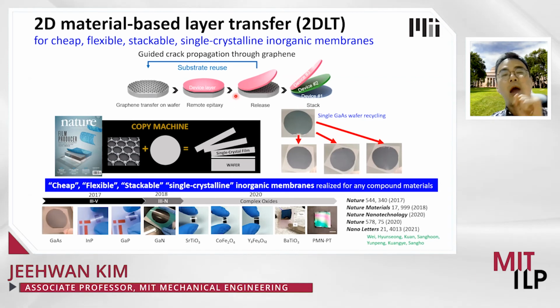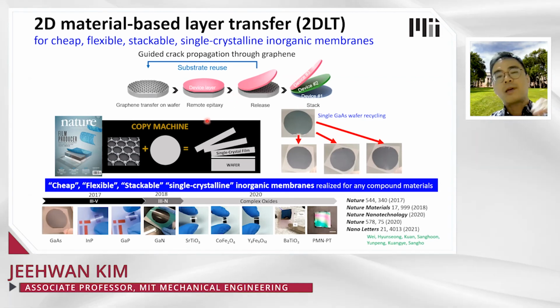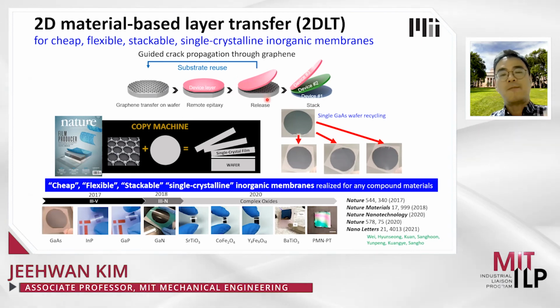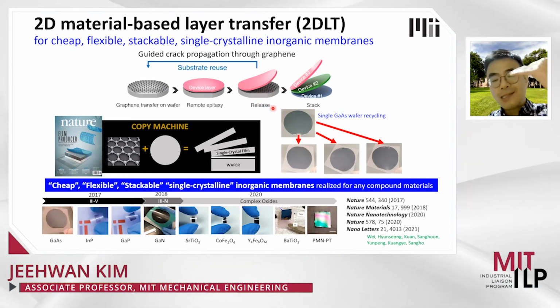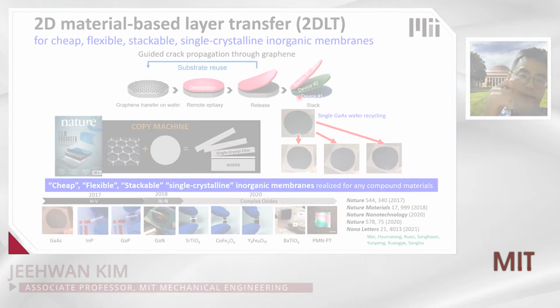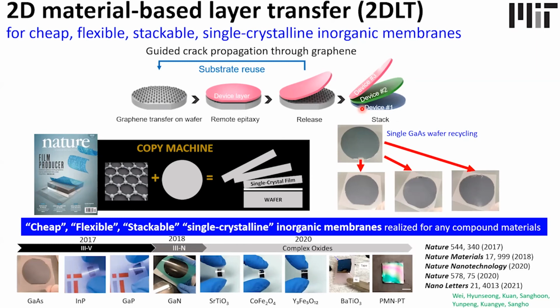At the same time, you are able to produce an ultra-thin device layer, which is freestanding, free from the substrate. That way, you can stack them up, you can bend them, so you have flexibility and stackability. At the same time, you don't sacrifice performance because it's perfect single crystalline. Also, we found a way to reuse this single substrate to produce many of these freestanding layers, so we can also reduce the cost of single crystalline freestanding membranes. So we are able to produce cheap, flexible, stackable single crystalline membranes.